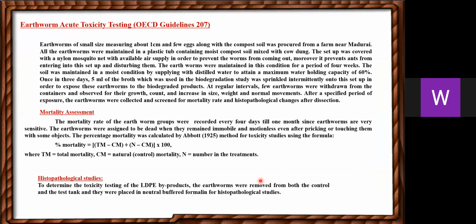Acute earthworm toxicity testing. The earthworms, small in size, measuring about 1 centimeter, were procured from a farm near Madurai and maintained in a plastic tub under controlled conditions. At regular intervals, the earthworms were withdrawn from the containers and observed for growth, count, increase in size, weight, and normal movements. After a specified period of exposure, the earthworms were collected and screened for mortality rate and histopathological changes. Mortality assessment was done by Abbott's formula, and histopathological studies were done in order to observe any adverse effect on the earthworms.